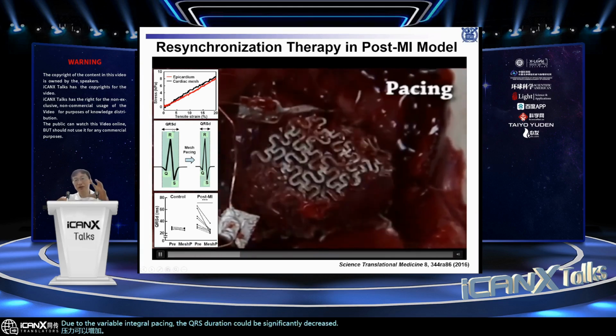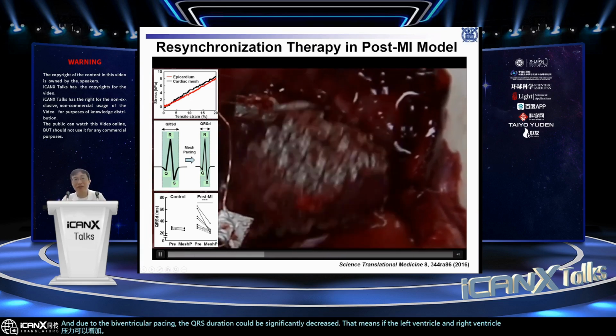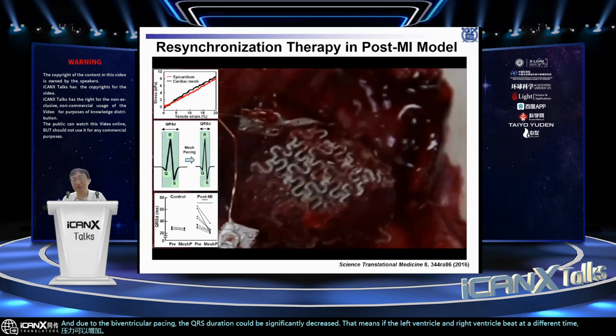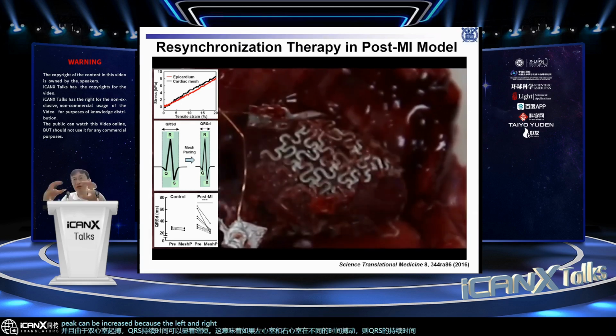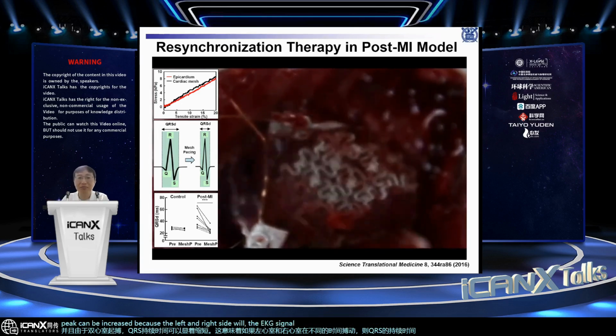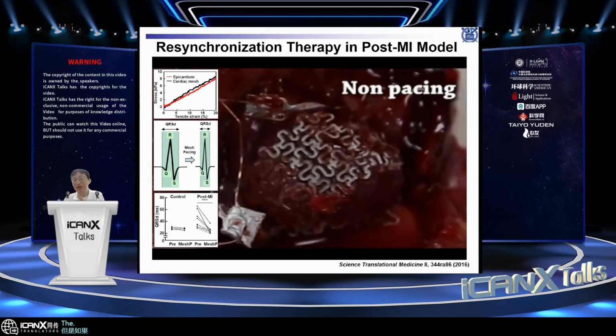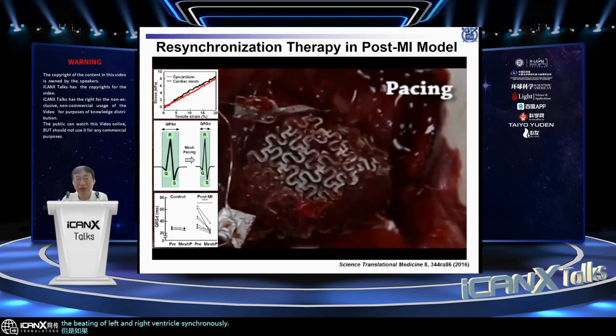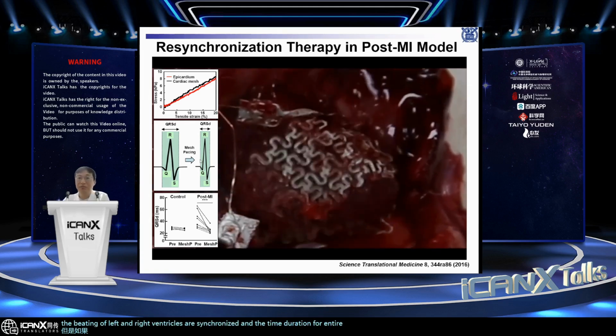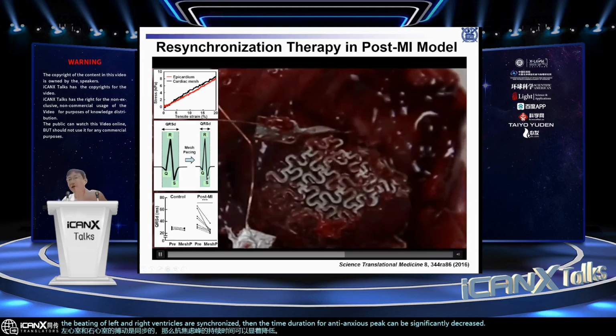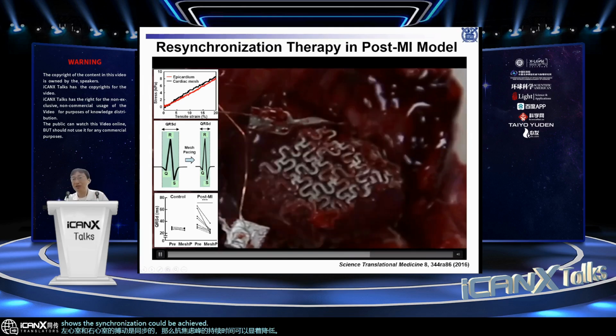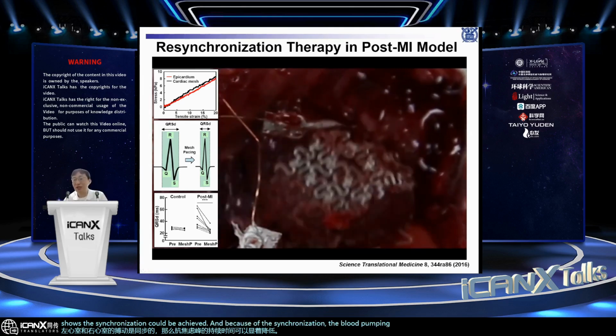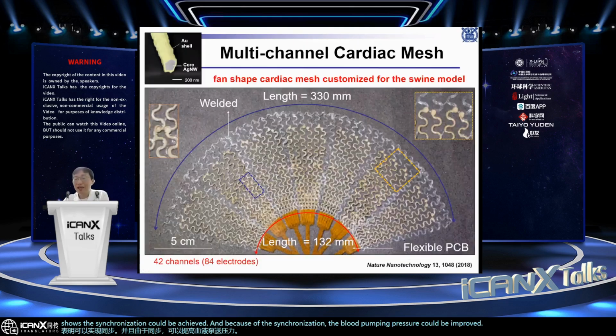That means if the left ventricle and right ventricle beat at different times, the time duration for the QRS peak can be increased because the left and right side EKG signals will be averaged. But if the beating of the left and right ventricle are synchronized, then the time duration for the entire QRS peak can be significantly decreased. That shows the synchronization could be achieved, and because of the synchronization, the blood pumping pressure could be improved. And later, we fabricated a larger, multi-channel device, customized for the pig model, the swine model.